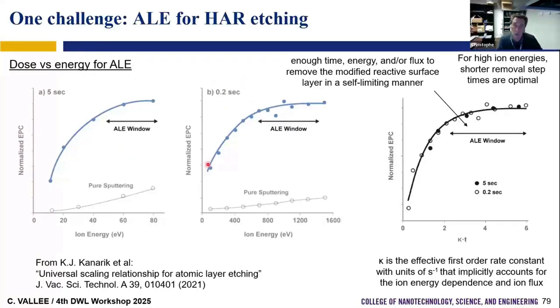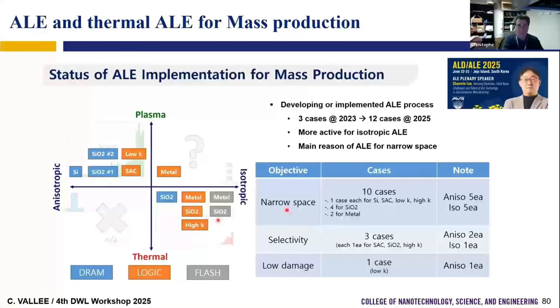So when we do a process assisted by ions, like when we want to add ions for ALD or when we want to have ions for ALE, in fact, what has been observed is that what is important is not the ion energy, it is the dose. So you may have the same dose if you use high energy, but you just have to reduce the time. So if you have a short pulse of square DC bias voltage, for example, you can have a very high voltage, short pulse, and you may still have an ALE-like process in high aspect ratio.